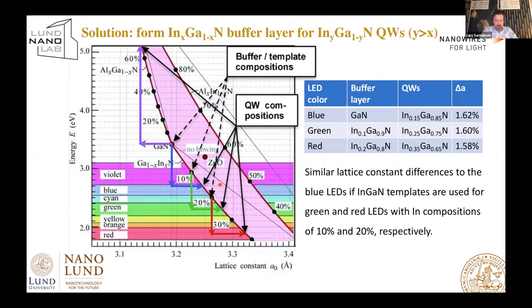So here you can see what you're doing in the Nobel awarded technology to make efficient blue LEDs. With gallium nitride as your lattice constant, for the quantum wells, you are adding indium to a very suitable range. So you're adding 15% indium. So this is now the composition of the quantum wells, 15% indium on gallium nitride.